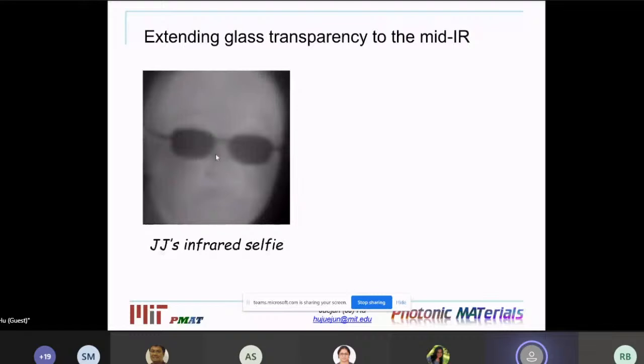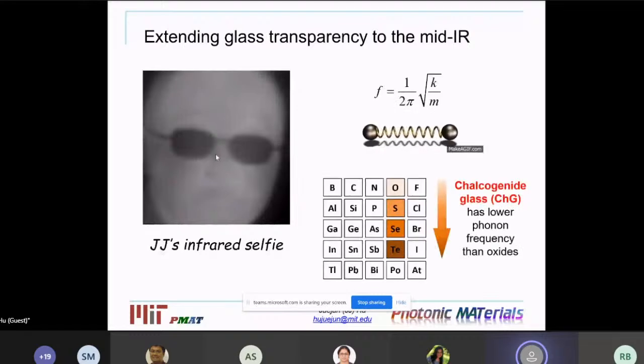Why is that? That has to do with the structure of oxide glasses. If you look at the absorption mechanism here in the infrared, the dominant absorption mechanism is actually due to optical phonons. The vibrational frequency of the phonons can be approximated with this equation here in the model of a harmonic oscillator. We're approximating essentially vibrating atoms as masses attached to the end of a spring. So in this case, the vibrational frequency scales with the square root of k. This is the spring constant, or in other words, the strength of the chemical bonds. And m, this is the reduced mass of the atoms.